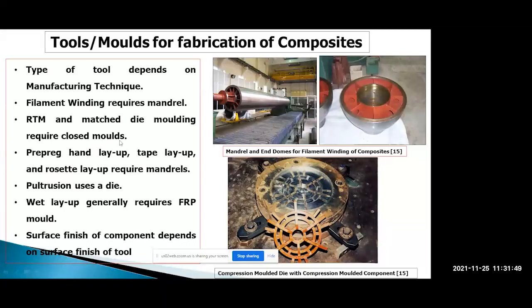RTM and match die molding require closed molds. Then pre-preg hand layup, tape layup, and rosette layup require mandrels again. Pultrusion uses a die. Wet layup generally requires FRP molds. We make fiber reinforced composite molds also. And the surface finish of the component depends on the surface finish of the tool. This surface finish we get for all our winding processes.